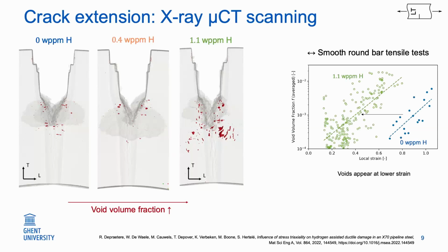And this is also something we could see in smooth round bar specimens, so simple tensile tests with hydrogen or without hydrogen. We can see that the voids start to appear at lower strains. So this is some kind of enhanced void nucleation because of hydrogen.